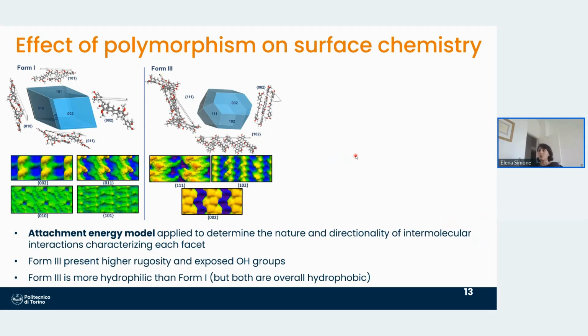We look at two different polymorphs, form 1 and form 3. Form 1 is the stable one, form 3 is metastable. However, it's very kinetically stable. So if we put it in ambient conditions, or also in suspension in water, it doesn't convert very quickly to form 1. It stays there for months, years, and so on.